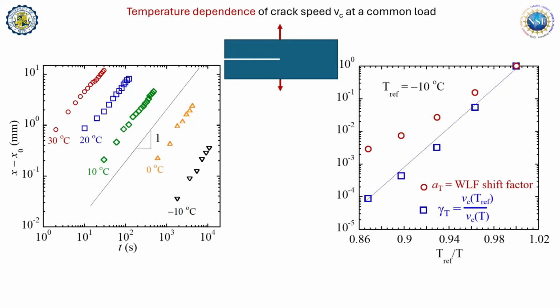You can do a strain test with a pre-notch, and you stretch it to the same level, and then you take it to your chamber at different temperatures. You watch how fast the crack will propagate at each temperature, and you calculate the speed of it. If you take a ratio of that speed to a reference, that's this line. That's the blue data, and WLF is the red. Nothing. WLF cannot capture it.